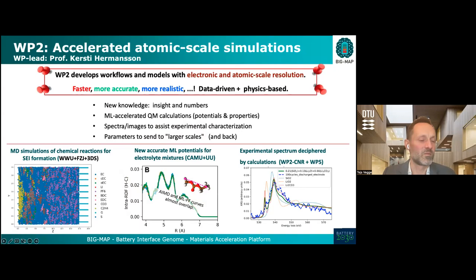So this is some examples from Münster first here of MD simulations of the chemical reactions that are at the core of SEI formation, where you can actually map out the beginning of species formed in the electrolyte that then subsequently are deposited on the electrode surface. You can also see the development of machine learned potentials for electrolyte mixtures.